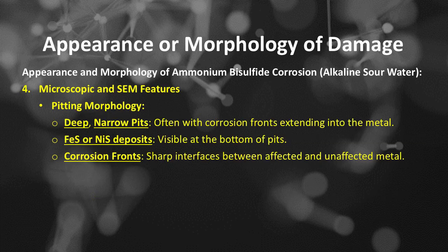Appearance and morphology of ammonium bisulfide corrosion or alkaline sour water. Number 4 is microscopic and SEM features. The first is pitting morphology: deep, narrow pits, often with corrosion fronts extending into the metal, ferrous sulfide or nickel monosulfide deposits visible at the bottom of pits, and corrosion fronts, sharp interfaces between affected and unaffected metal.